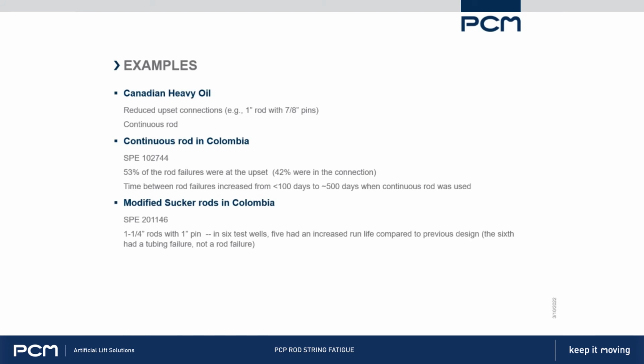But again, an 1 1/4 rod with a 1-inch pin, so they're getting good torque capacity, but a reduced coupling size. Out of the 6 test wells, they have increased run life in 5 of them. The 6th one had a tubing failure, not a rod failure. So again, showing these techniques can work.